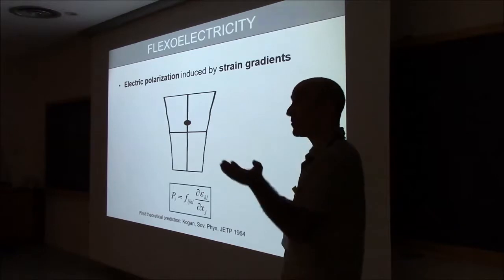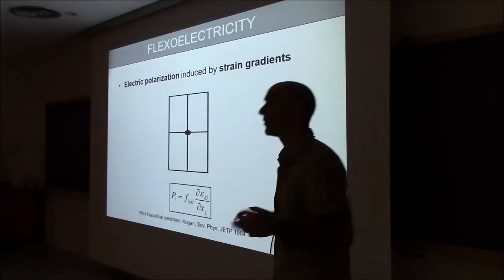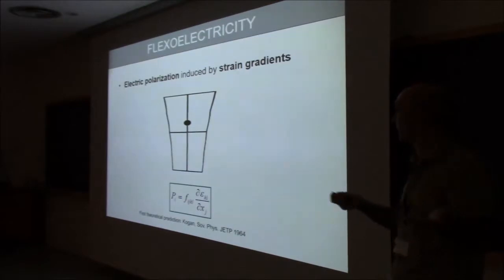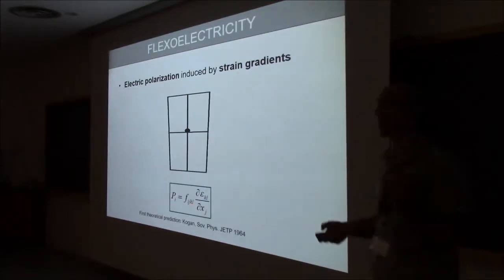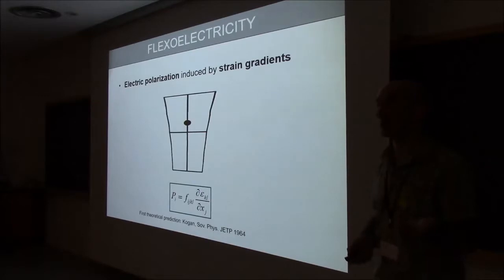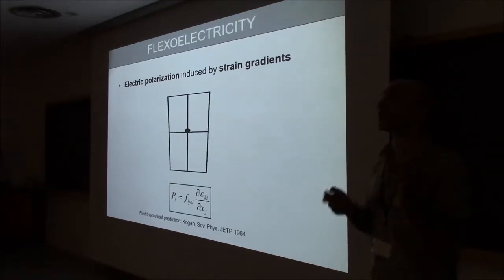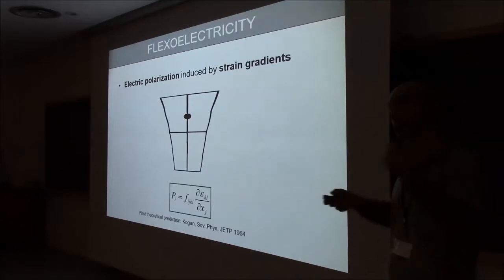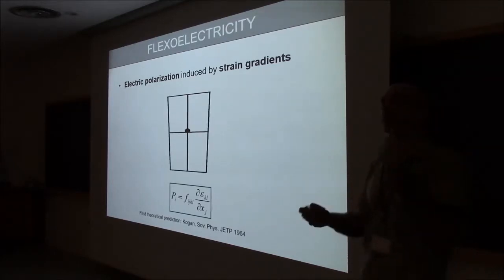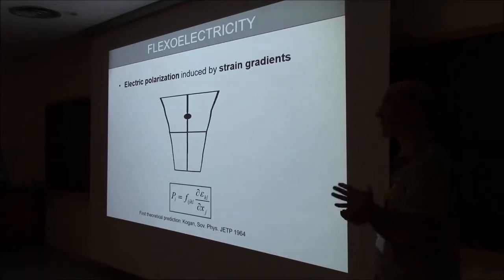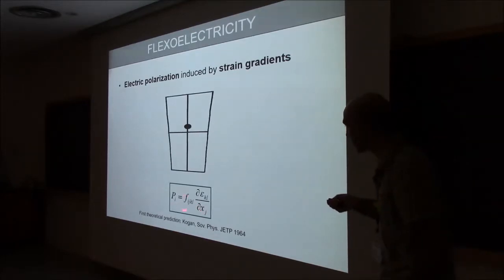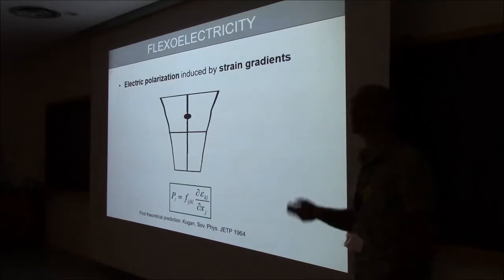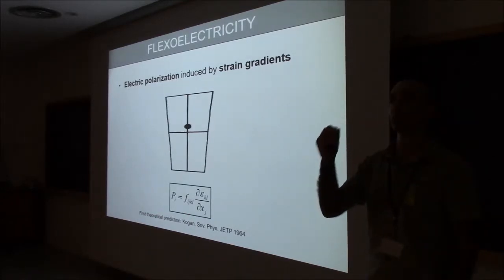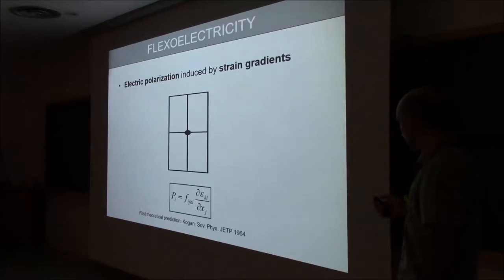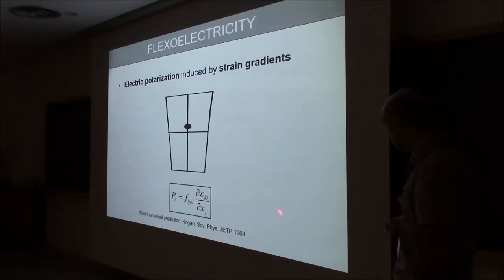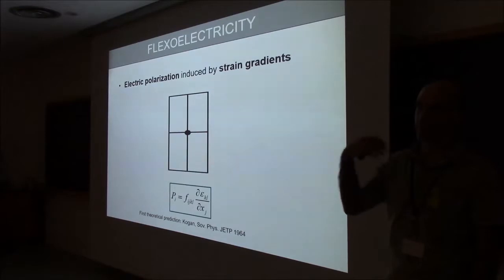Which means that the flexoelectric tensor can be even parity. It's a fourth-rank tensor, which means that it's allowed by symmetry in pretty much any material. You are not limited to non-centrosymmetric materials. If you remember, piezoelectricity is only possible in materials that have an asymmetric unit cell. Here you can start with a symmetric unit cell. The flexoelectric tensor allows you to do so because the strain gradient itself, the deformation itself, is what breaks the symmetry. And as so many things, this was first proposed in the Soviet Union many, many decades ago.